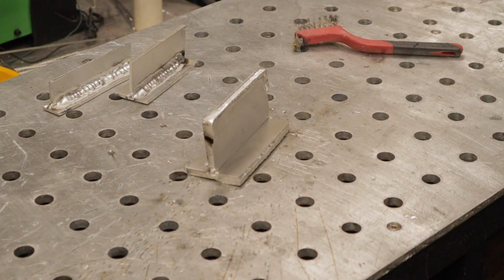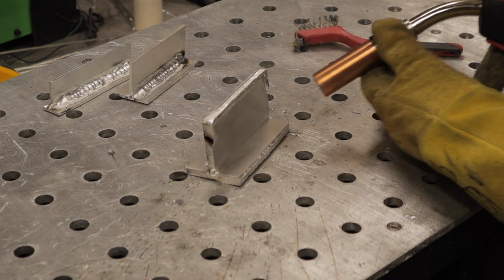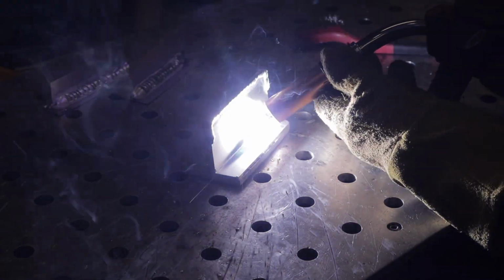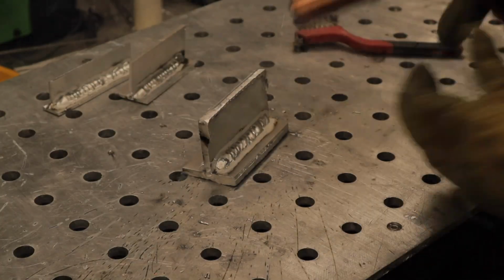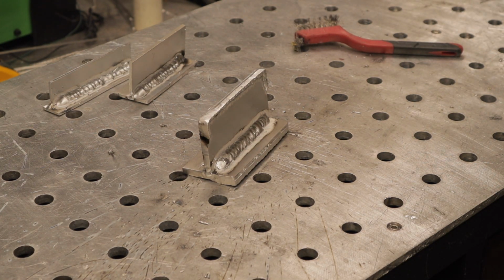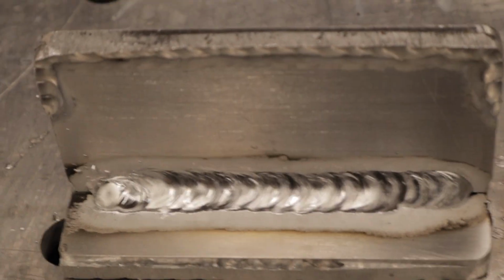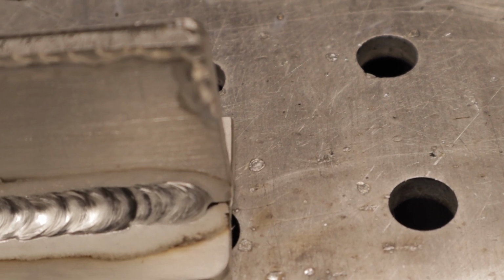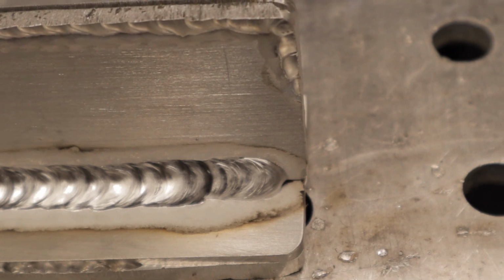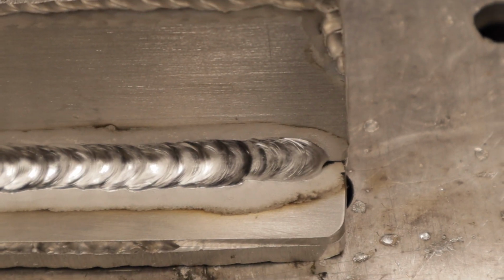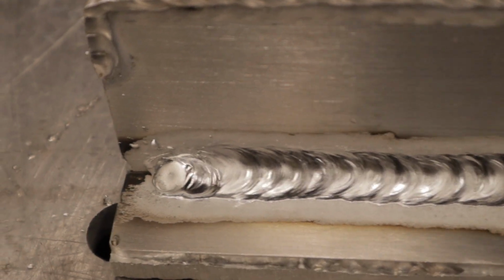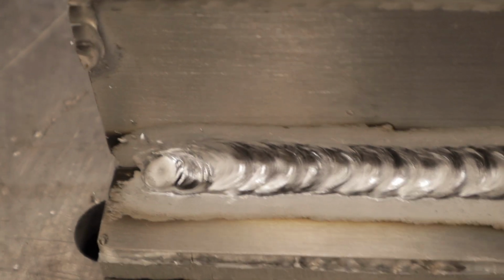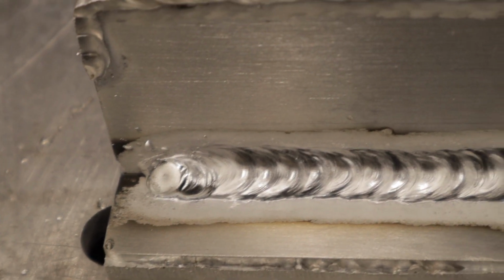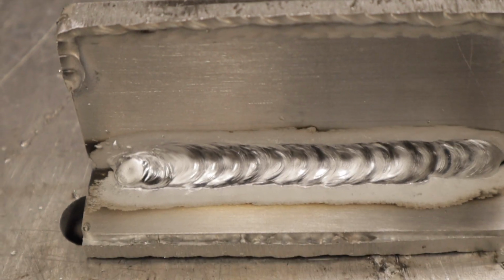Alright, this is 1/4 inch, 6061. Alright, so you can see I haven't brushed it. We got good cleaning action. It was a little offset a little bit at the beginning there, and then once I released and went into the regular amperage, it flowed nice. And then you can see I filled the crater at the end with the last of the 4TL settings. But that's 1/4 inch, 6061.